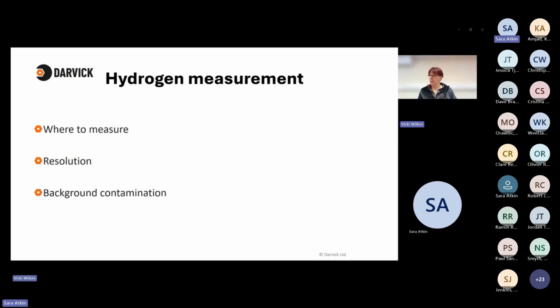But the other question is really how you are measuring hydrogen. So as I said, the actual purity of the hydrogen is extremely important to the amount of embrittlement and the effect it has on the material. So most tests look for an N5, so that's 99.999% pure hydrogen. But by the time you've put that through a test system, through various pipes, valves, seals, through the sample itself, can you be confident that you've still got that same purity of hydrogen at the end of the test as you had at the beginning?